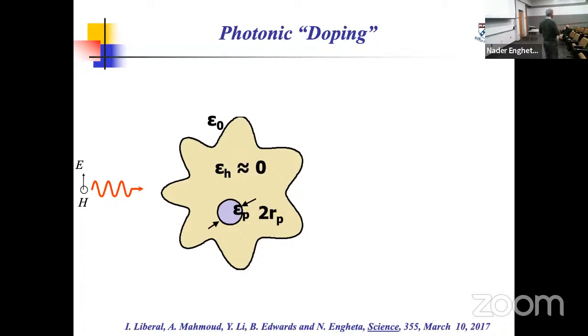what happens to the scattering of this? Without going into the detail, because I don't have time: if I have the original column, which is the yellow shape there, and I send the wave with this TM polarization, you get certain scattering. Now, you put the single dielectric rod there, and obviously you're going to get different scattering. But for the observer sitting outside, this different scattering is associated with what effective parameter? Has effective epsilon changed, or has effective mu changed? You would say, well, obviously epsilon, because I started with epsilon zero and I put a dielectric there. But actually that's not the case.